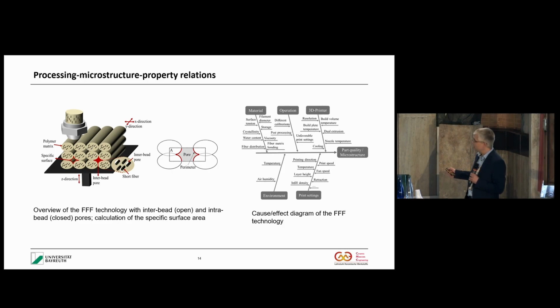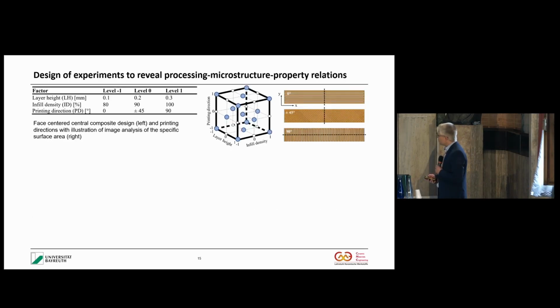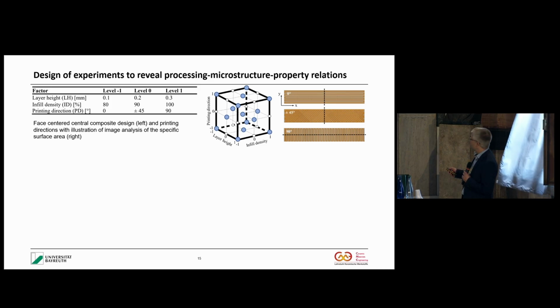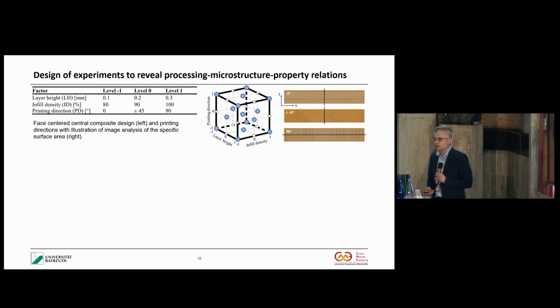So we then went a step further to optimize this process. If you come to fused filament fabrication and study the influencing factors closely, you realize there are a lot of factors for additive manufacturing that you can change and that also change the processing and therefore the microstructure and the properties. That's why we had to make a selection. The easiest one is first of all the printing direction. We have three different directions: 0 degrees, 90 degrees, and plus minus 45 degrees.